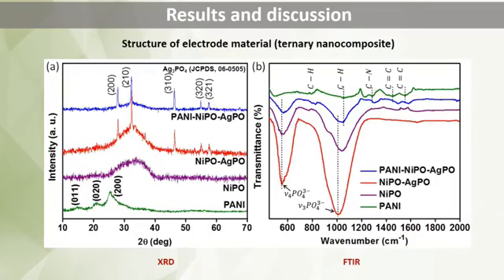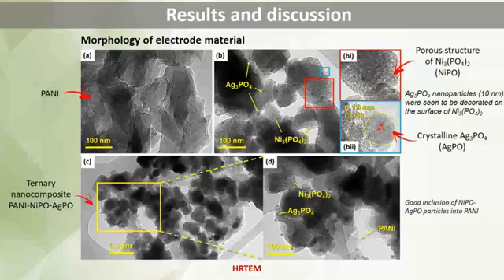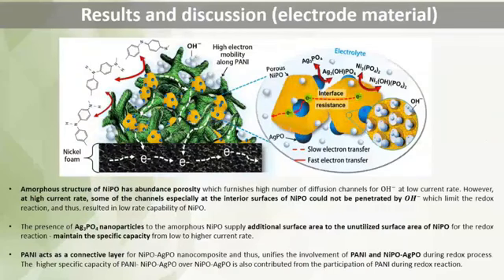And some of the results show that the ternary nanocomposite has a very good complexation, which can be observed from the XRD and also the FTIR. This is shown by the creation of new peaks, the shift in the peaks, and also the intensity of the peaks. And then HRTEM results show that silver phosphate nanoparticles are decorated on the surface of nickel phosphate, and a very good inclusion of the nickel phosphate and silver phosphate particles into the polyaniline. And then here the result shows that the amorphous structure of nickel phosphate has abundant porosity and the presence of silver phosphate nanoparticles